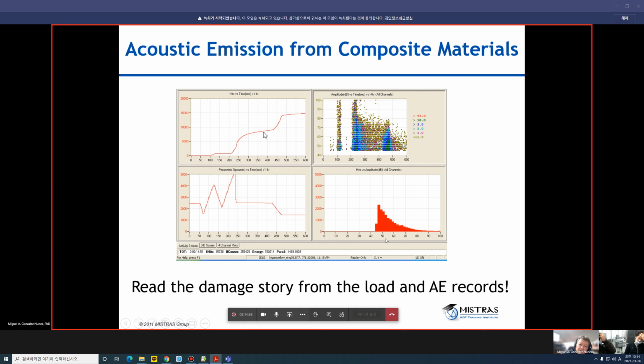So you see the relevance here: when there is present damage, we have the presence of secondary acoustic emission, maybe related to frictional emission due to the formation of new surfaces on cracks created in the material.